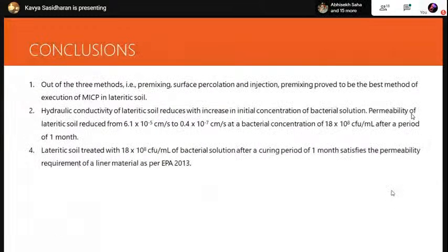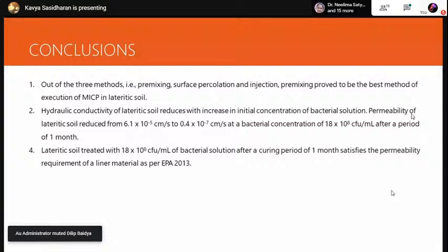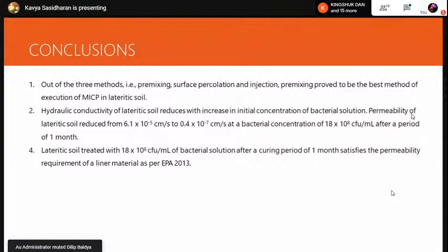So the concluding points are: out of the three methods, the best method for treating lateritic soil through MICP is premixing, and the hydraulic conductivity of lateritic soil reduces with increase in initial concentration of bacterial solution. And as already told, the soil treated with 18 into 10 raised to 8 CFU per milliliter of bacterial solution, with a curing period of 1 month, satisfies the permeability criterion as given by EPA 2013.